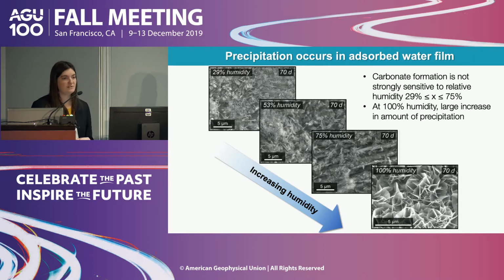So for example, shown here, we're looking at brucite surfaces reacted with atmospheric CO2 for 70 days as a function of humidity, with increasing humidity from upper left to lower right, so going from 29% to 53% to 75 to 100%. And these little flaky things you observe at the surface, that's our magnesium carbonate minerals identified with infrared spectroscopy. And so you notice these are present in all humidity conditions, but there's very little overall reaction at humidity less than 100%. There's very little difference between these humidity conditions, less than 100%, and we didn't observe continued reaction throughout the experiment, which was over a year long.